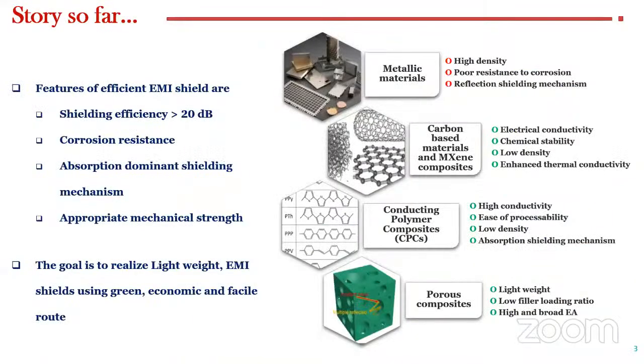The features of an efficient EMI shield are: shielding efficiency should be greater than 20 dB. At 20 dB shielding efficiency, the shield is blocking 99% of radiations incident on it. It should also have corrosion resistance, an absorption-dominant shielding mechanism, because if it is reflection, the reflected waves again pollute the environment, and appropriate mechanical strength. Conventionally, metallic materials were used for shielding, but due to their heaviness and corrosive nature, they were replaced by carbon-based materials, MXene composites, conducting polymer composites, and porous composites.